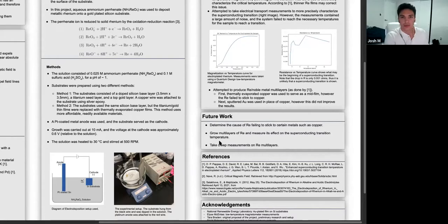So that's definitely something to try continuing in a future version of this work, is getting those multi-layers to function properly, because other groups have found that doing these multi-layers can nearly double the critical temperature, which is huge for superconductors. And then another possible idea in the future is if you can get these multi-layers to work, try doing transport measurements and experiment with vortex pinning and the different dynamics of superconductivity within the material.